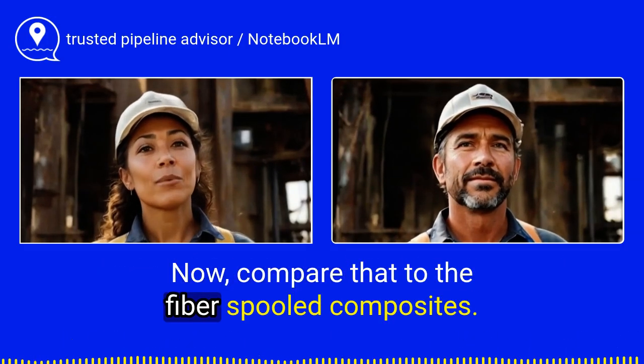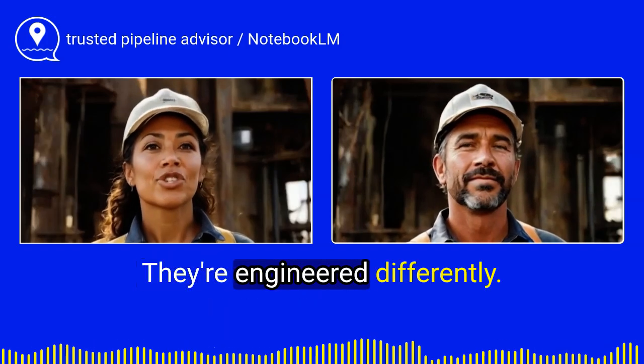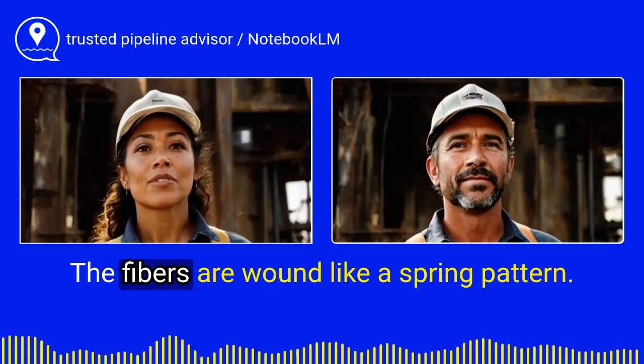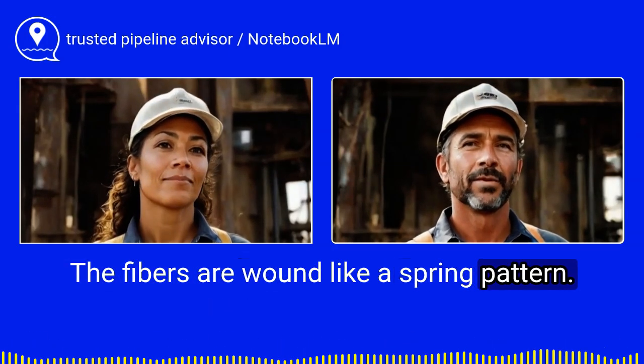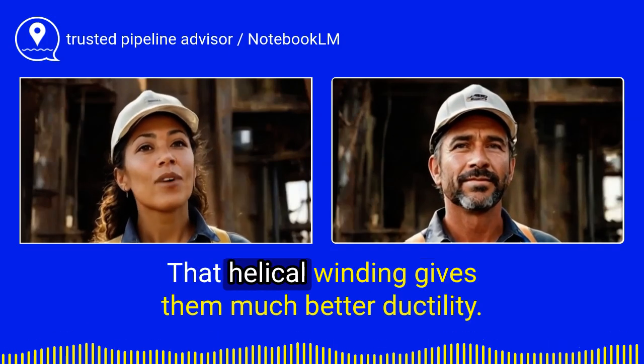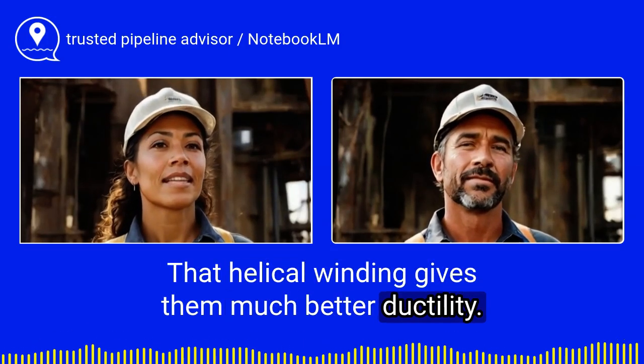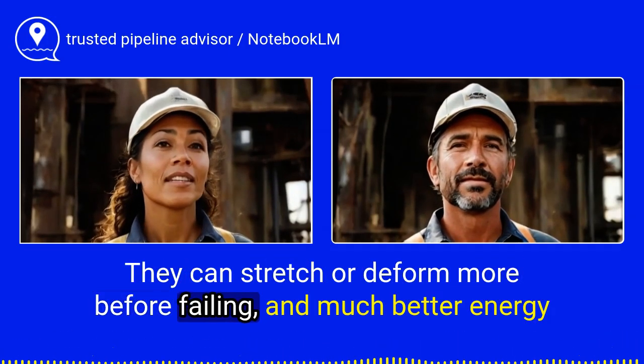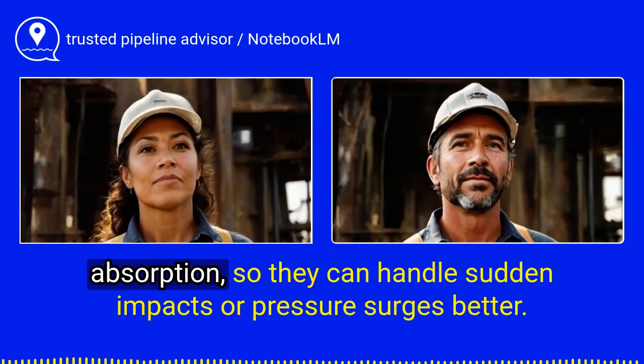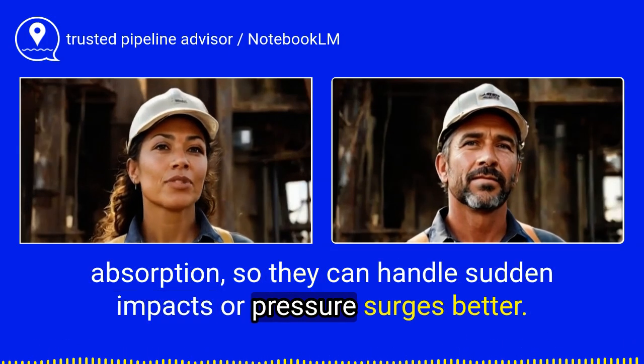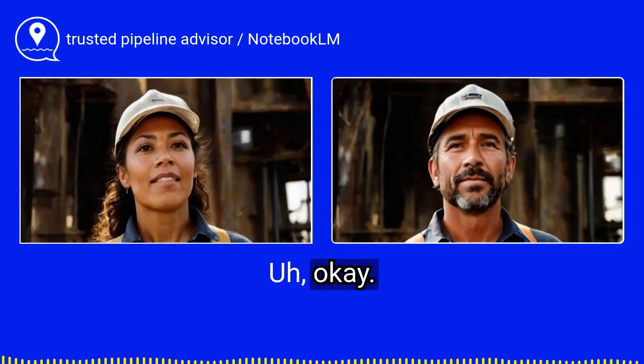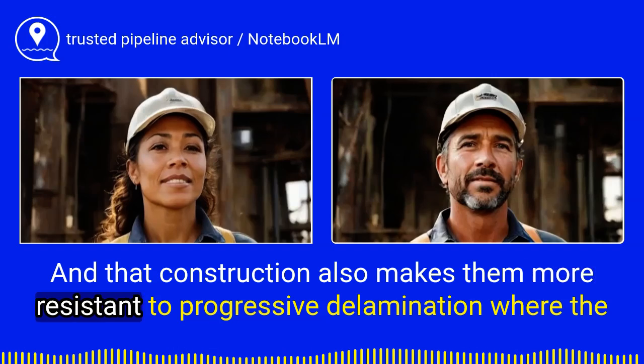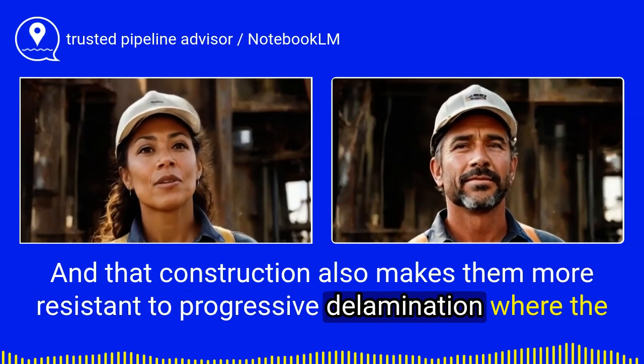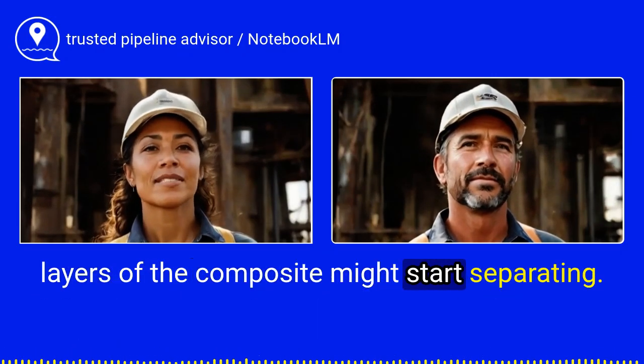Now, compare that to the fiber-spooled composites. They're engineered differently. The fibers are wound like a spring pattern. Okay, and what does that do? That helical winding gives them much better ductility. They can stretch or deform more before failing, and much better energy absorption, so they can handle sudden impacts or pressure surges better. And that construction also makes them more resistant to progressive delamination, where the layers of the composite might start separating.